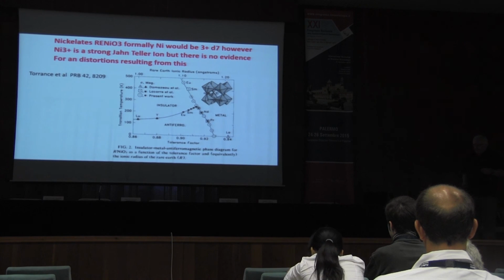Now, the nickelates have a very, very rich phase diagram. Jerry Torrance did this many years ago, where depending on which rare earth you have, which has to do with the size of the rare earth ion, you have semiconductor metal transitions and insulator to antiferromagnetic transitions. For example, here you would go from a metal to a semiconductor or an insulator and to an antiferromagnet over here.